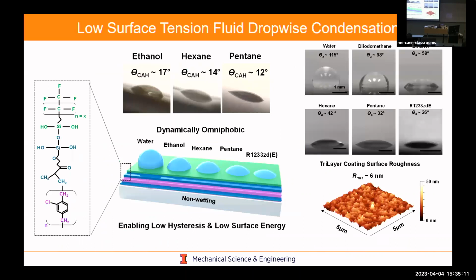And so one thing we've been developing is a multi-layer, we call it a tri-layer coating formulation, to be able to repel low surface tension fluids. We first deposit a parylene C layer, which smooths out the surface and makes it very flat, atomically flat if you look at an AFM scan. We then have a binding layer, which increases the wet adhesion. And then we have a capping layer, which lowers the surface energy. And it turns out if you look at ethanol, hexane, pentane, as you go down in surface tension, you could still repel these liquids with fairly low contact angle hysteresis.